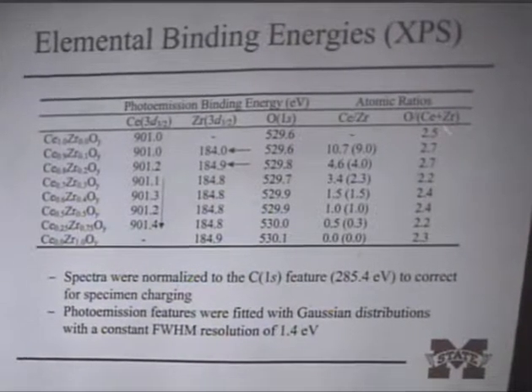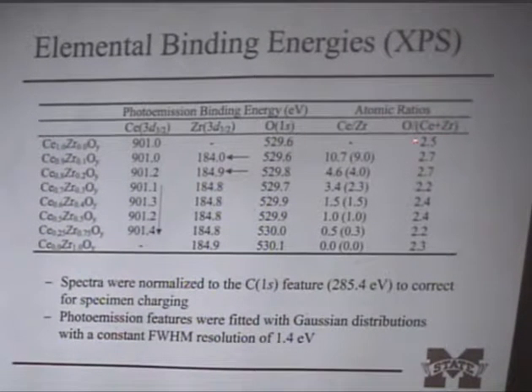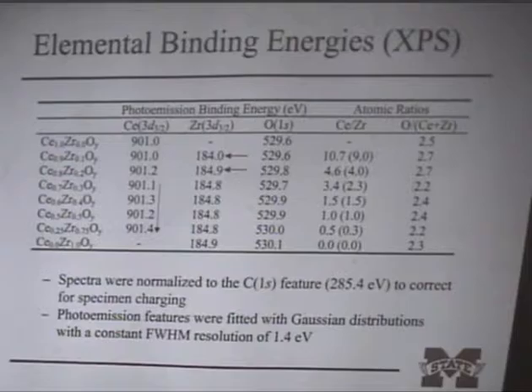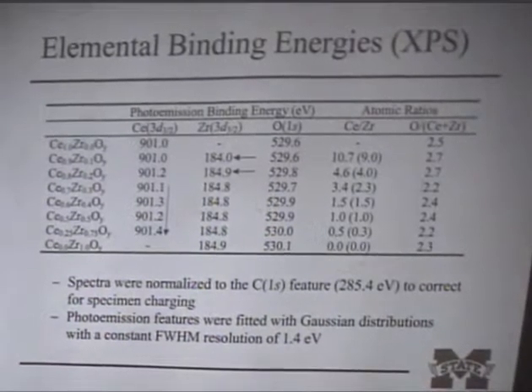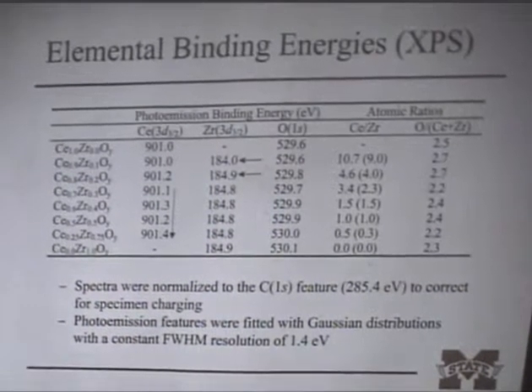Now, what was more important was we wanted to get a feeling for the amount of oxygen that might be available at the surface for bonding. And I'm going to apologize for this kind of ugly plot that I'm about to show, but I think it illustrates just a couple things. Okay, there's clearly a lot of scatter here, but in general, we see two ranges. We get a ratio of about 2.6 to 2.7, and then when we get to 30 atomic percent zirconium, we see it step down just about here.